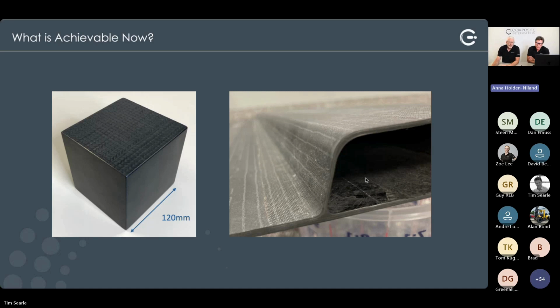In this slide, we've got a typical spar cap component made largely from UD carbon. It's about 120 millimeter cube that we've cut from a sample, and it's infused. We've got it with us, so try not to drop it. But on the right hand side, perhaps a much more contrasting, skinnier aerospace part, where the effort that goes into this to ensure that we can infuse this successfully at the right sort of quality, there's just as much effort that goes into ensuring that we can faithfully produce very, very tight, high tolerance radii on liquid resin infused parts. And so, there's a couple of contrasting applications there.